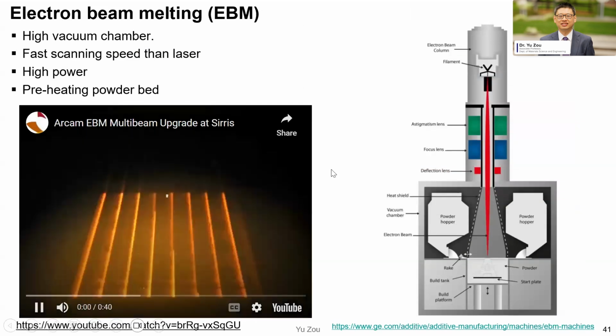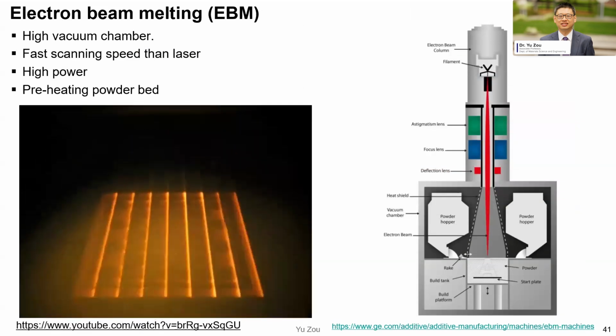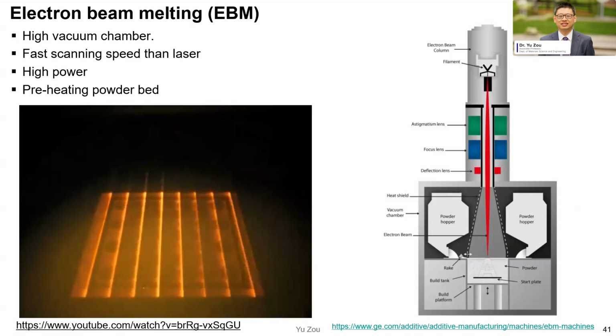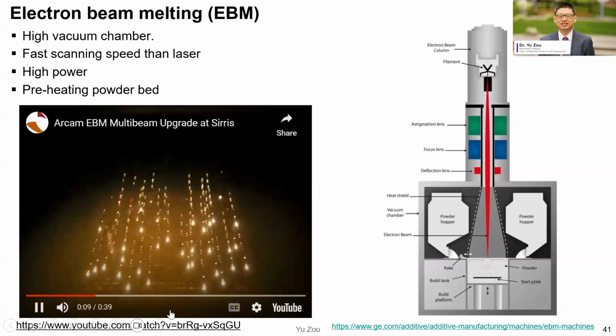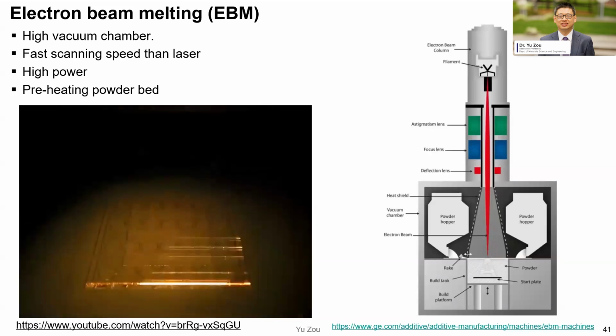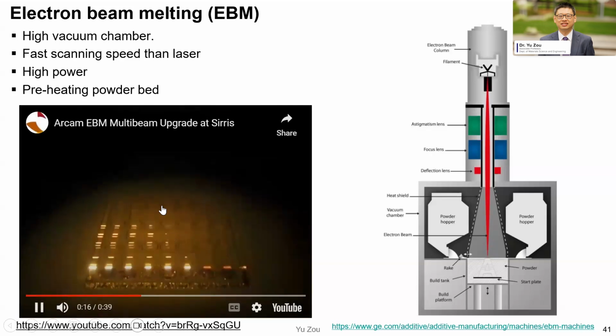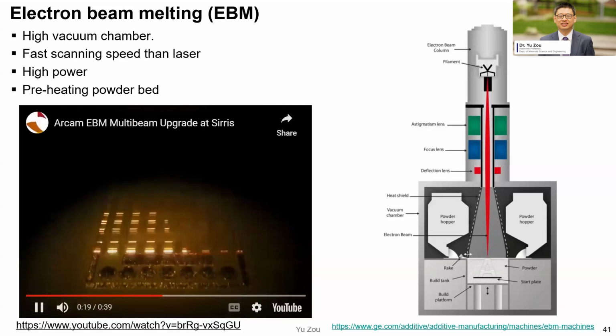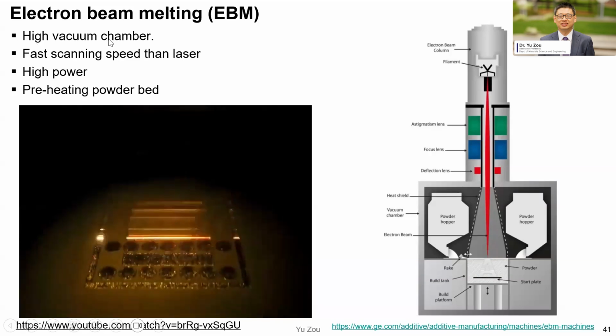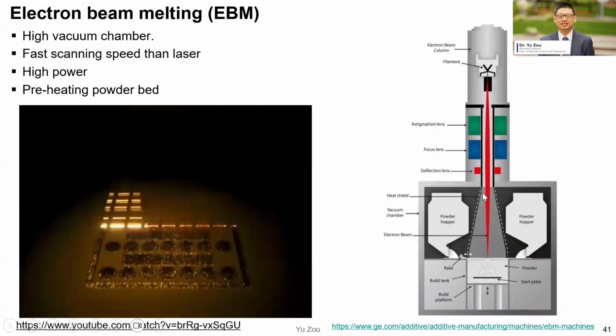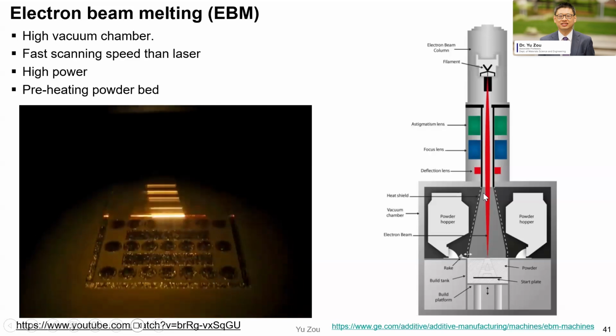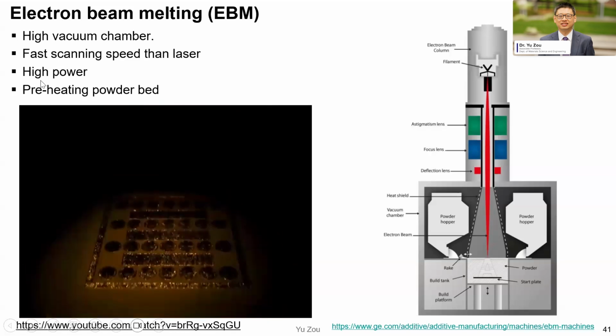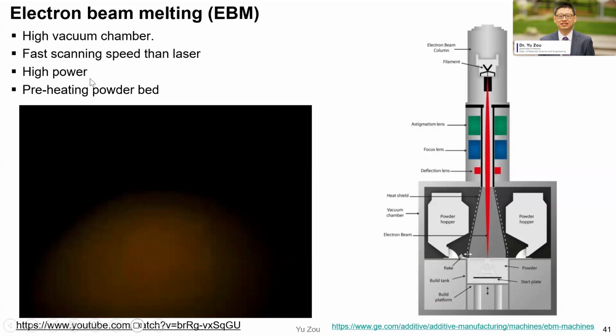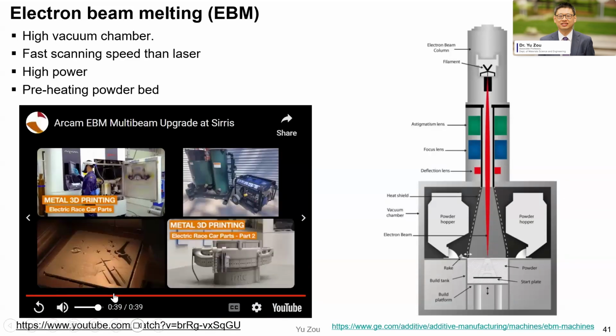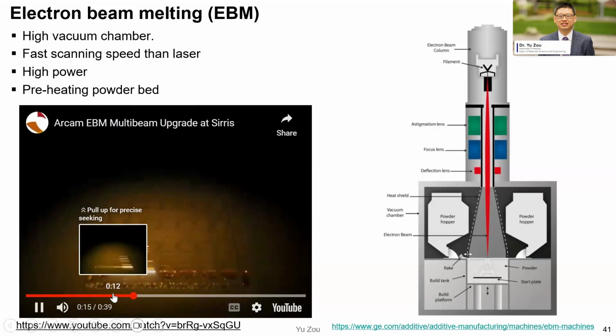Another technique that is very similar to laser powder fusion is called electron beam melting, or EBM. In this technique, we also use a powder bed, but the energy source is different. It uses an electron beam, similar to a scanning electron microscope, but in a vacuum here, instead of using argon as in laser powder fusion. The E-beam provides a faster scanning speed and a high power energy density, and we can also have a preheated powder bed.